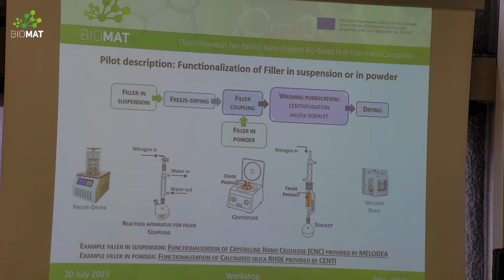Pilot 8 deals with the functionalization of fillers in suspension, like the crystalline nanocellulose provided by MELODEA, or in powder, like the calcinated rice husk silica provided by CENTI, with bio-polyol. The functionalization of filler involves mainly three steps. The first one is the filler coupling, which is performed in a two-neck round bottom flask equipped with reflux condenser under inert atmosphere and under vigorous stirring. The second step is the purification of the crude product performed by using a centrifuge or a Soxhlet apparatus. And the third step is the drying of the purified product.